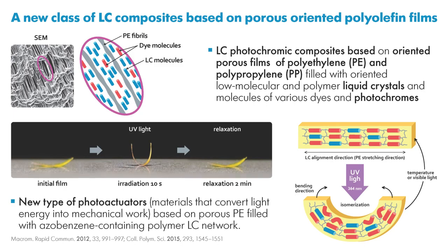In particular, we have created a new type of photoactuators, materials that convert light energy into mechanical work. These photoactuators are based on porous polyethylene filled with azobenzene-containing polymer liquid crystalline network. When such films are irradiated by UV light, isomerization of photochromic groups occurs in the top layer of such films. This process results in transition of nematic aligned phase to isotropic one.